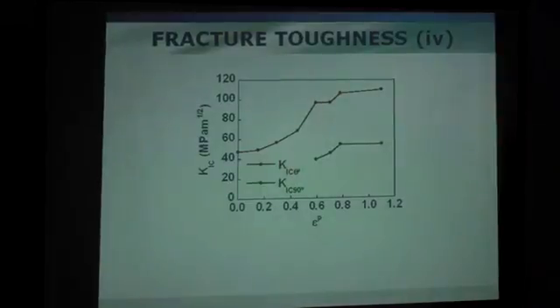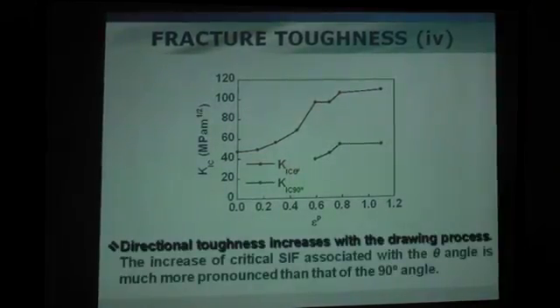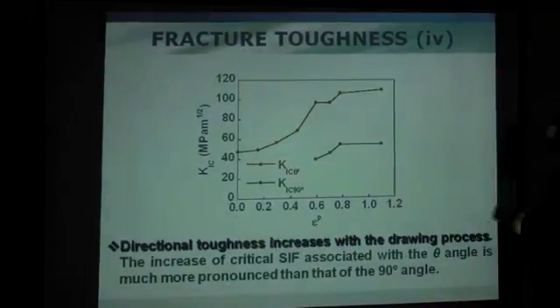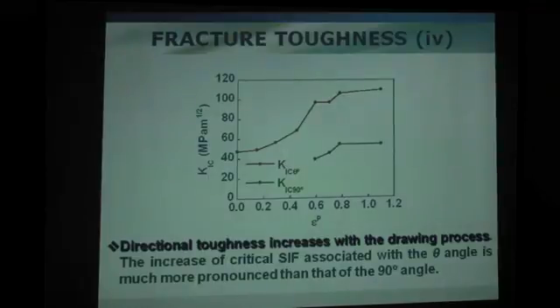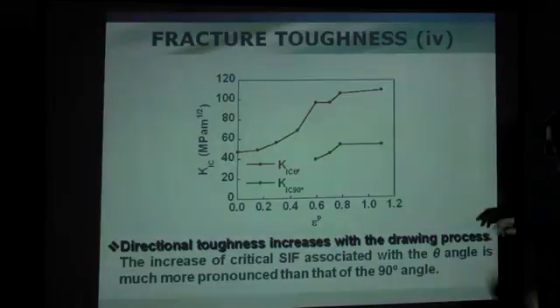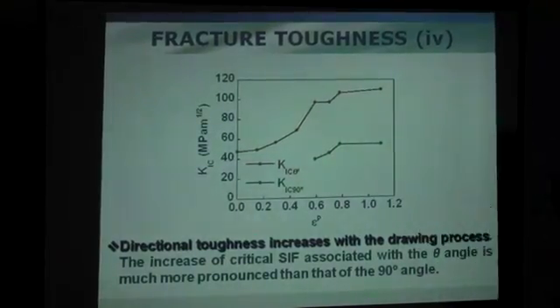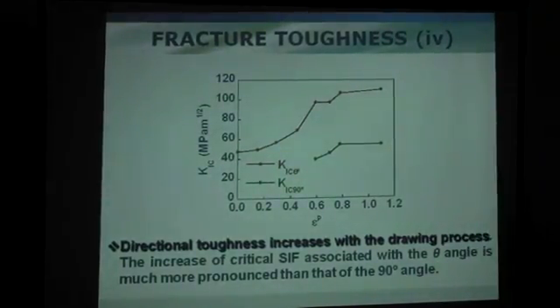Then we obtain the following ideas interpreting this plot. A directional toughness or a directional critical stress intensity factor or a directional energy release rate which increases with the drawing process. The increase of critical stress intensity factor associated with the theta angle is much more pronounced than that of the 90-degree angle. Okay? Here we have a clear increase, but in 90 degrees we have similar energies with independence of cold drawing for splitting or delamination. That's logical for the debonding.